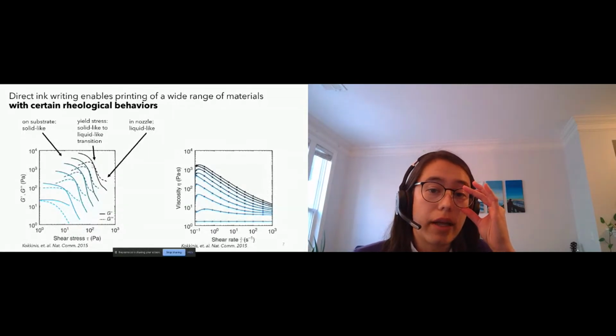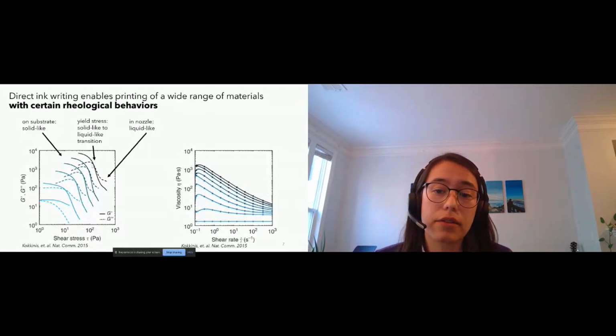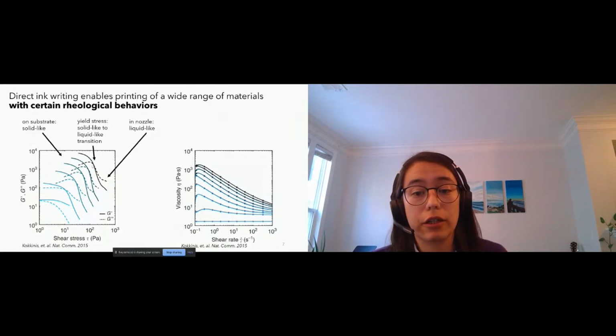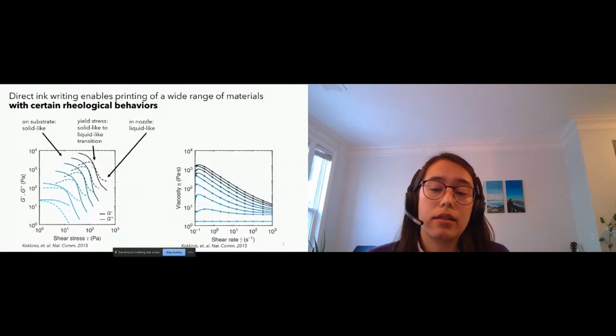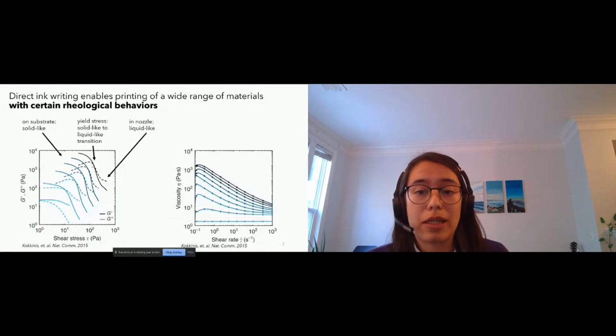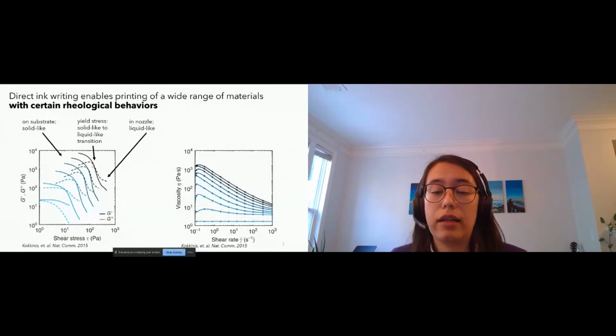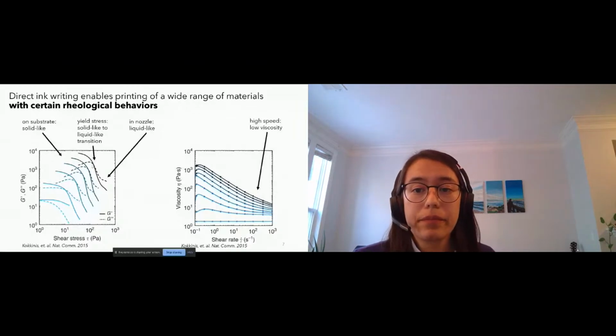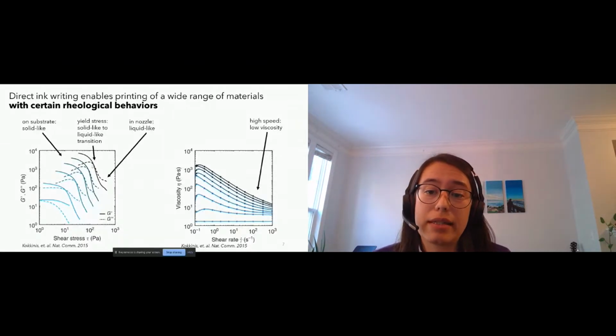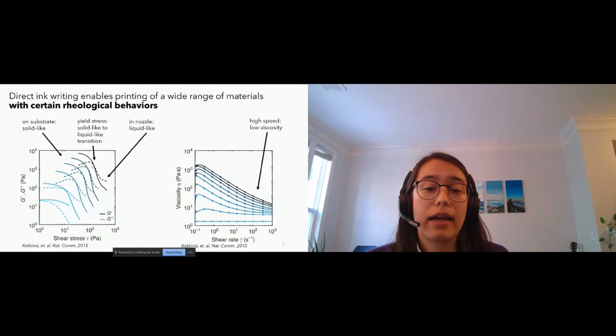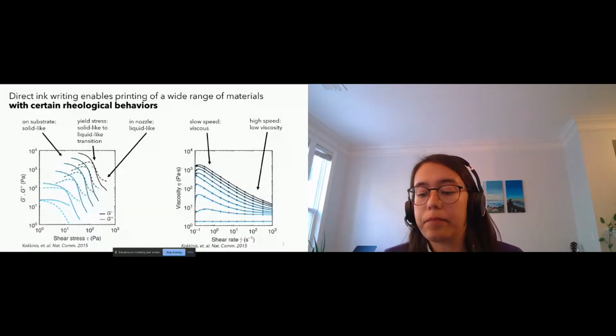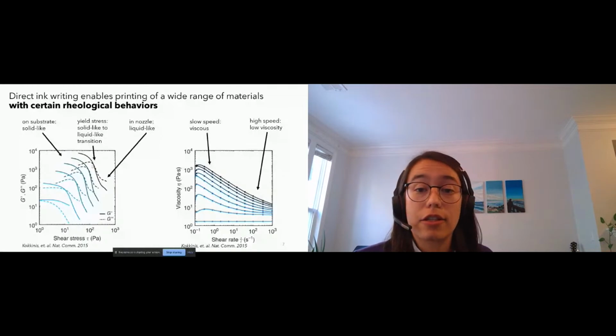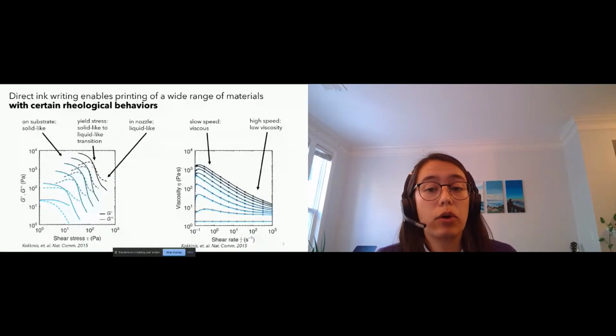Another way that you can look at the rheology of these materials is using viscosity curves. So we're looking at the viscosity as a function of shear strain rate here. And what you can see is that these are shear thinning materials. So as you increase the shear rate, you decrease the viscosity. What that means is if you print at high speeds, that'll decrease the viscosity of the ink, and that means you can still get it out of the nozzle without using exceptionally high pressures. At slow speeds, such as when the ink has just come out of the nozzle, it's going to become more viscous and it'll resist flow and be able to hold its form.